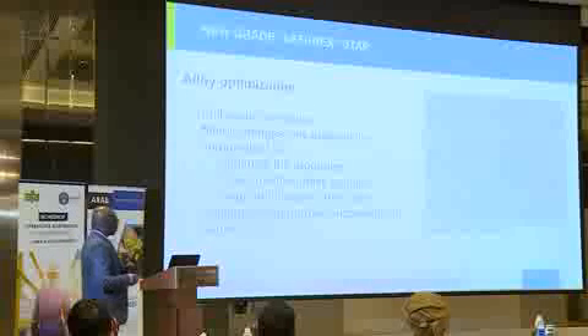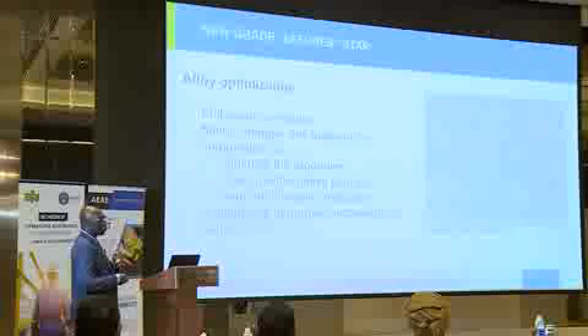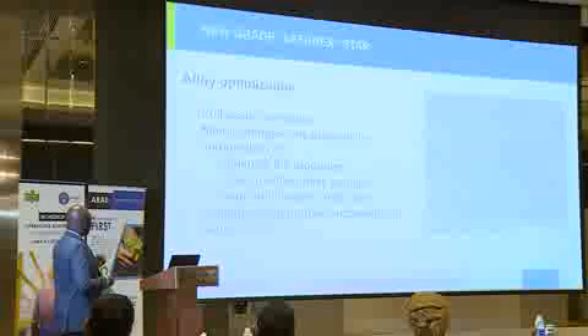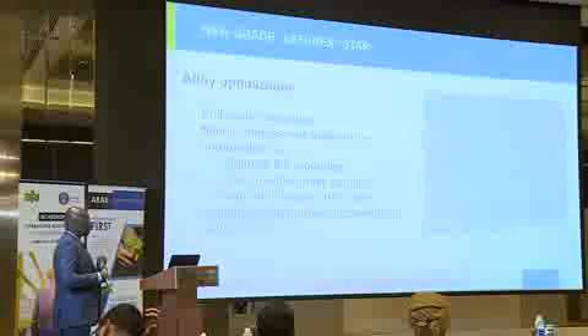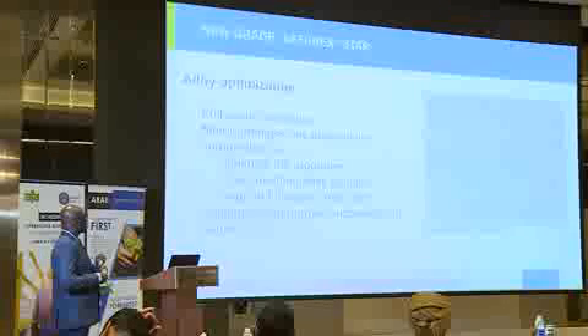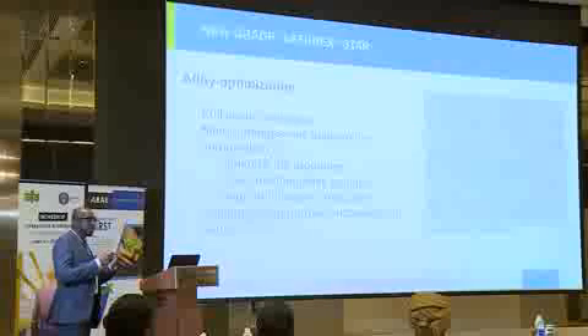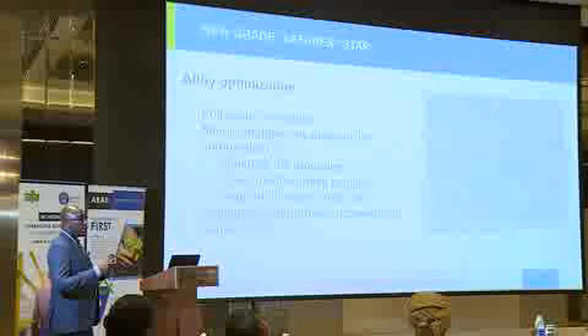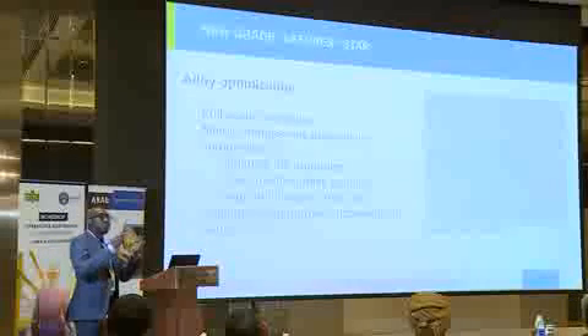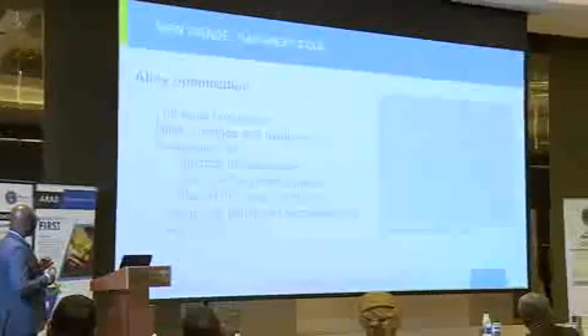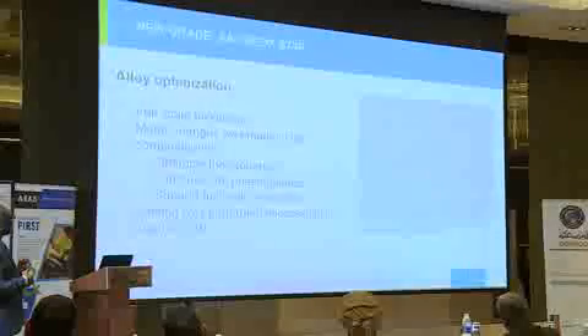This is a microstructure from the first casting of this material, which was done in 2016. Between then and now, we have a full production, commercial production of Safurex Star. In order to go into full production, of course, the chemical composition and a few things have to be tweaked to improve it and to make it better in line from the laboratory conditions to actual production. And we've optimized the composition, fine-tuned the phase balance, and this supports full-scale production.